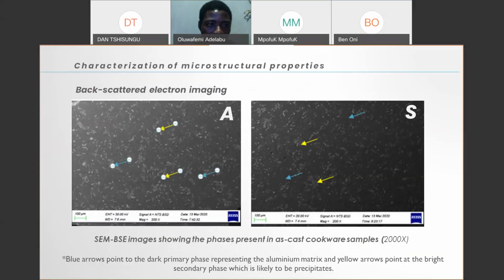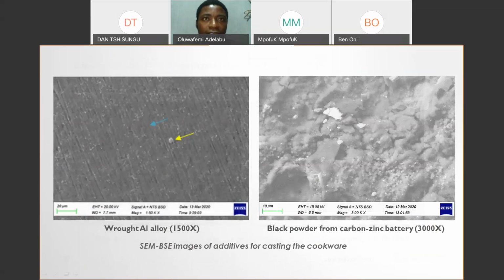So the characterization of microstructural property using backscattered electron imaging is shown on the screen. Here we have the image from sample A and then from sample S. The blue arrow points to the dark primary phase representing the aluminum matrix, while the yellow arrow points at the bright secondary phase, which is likely to be precipitate. Now, these are the images of additives for casting the cookware. Here we have the wrought aluminum alloy, and then we have the black powder from the carbon zinc battery.